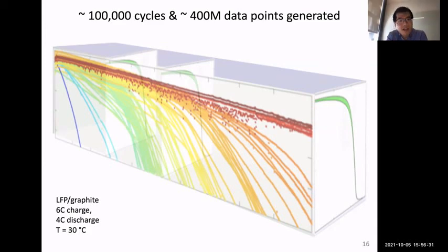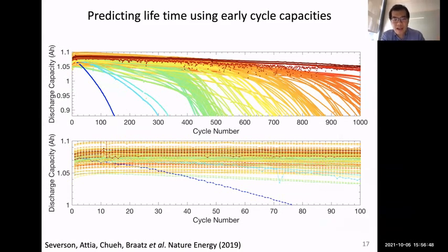This data set here, which we have collected, is about 400 million data points generated over about a year's time. It constitutes a bunch of batteries aged under different conditions to produce very different characteristics. If I show you this data set, I would represent it by showing you the performance of the battery, which is typically recorded in the energy it contains, over the number of cycles I age the battery. Here we are using our aging conditions to deliberately vary the lifetime of the battery. So some batteries last only 100 recharge cycles, while other batteries last 3,000 recharge cycles.